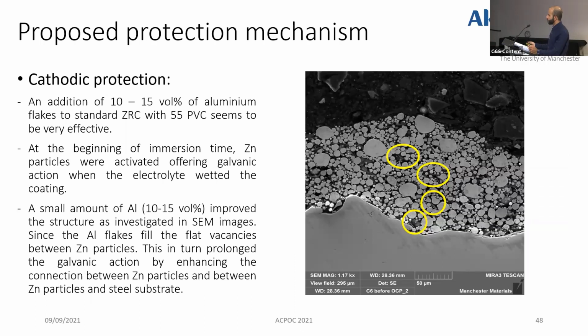So finally, the proposed protection mechanism of these zinc aluminum coatings, I can summarize it by two main properties: the cathodic protection and galvanic action, and the barrier properties. So the addition of 10 to 15 volume percent of aluminum seems to be very effective in zinc-rich organic coatings. At the beginning of immersion, zinc particles were activated, offering galvanic action when the electrolyte wetted the coating.